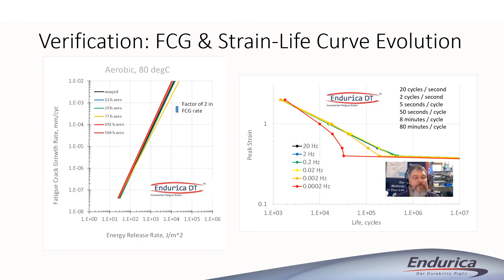The end result of setting all these material properties up is a fatigue crack growth rate curve that evolves with time. If you look at the curve on the left-hand side of the slide, you can see a set of curves that have been output from the code for various times. The black curve is the unaged crack growth rate curve, and then as you go from cooler colors to warmer colors, you're seeing the crack growth rate curve that corresponds to that particular aging time. On these log-log scales, the changes to the crack growth curve seem very modest, but if you look at the size scale bar, you can see that the blue size scale bar is about a factor of two. So the crack growth rate does go up or down by a factor of two or three over the aging life of this particular material.